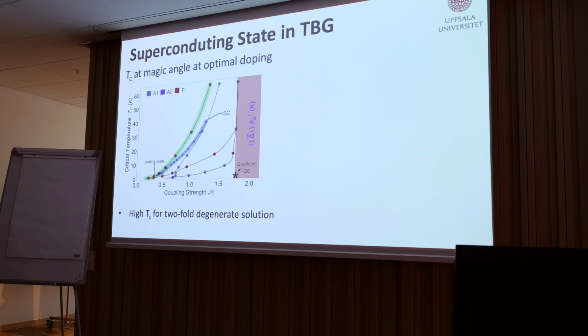But what's more interesting, I think, from a physics point of view, is actually what the results are. So here is the critical temperature as a function of coupling strength. Remember, I said the one single parameter I had in my calculation was this J. So I often have to tune things as a function of J because I don't know what J is. In single-layer graphene, there's a critical coupling to reach superconductivity, and that sits in this region here. But if it's bilayer graphene, I have a lot of density of states, so I get the finite Tc's at a lot lower temperatures.